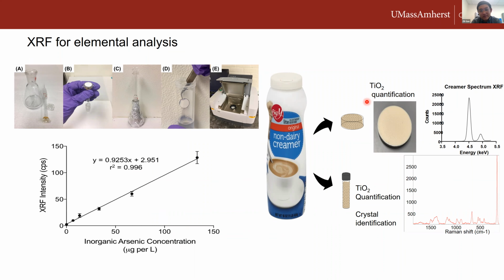It is very similar to Raman. It will be minimally invasive to your samples. Usually, you don't need a very complicated sample preparation procedure. Sometimes you can directly measure your sample in the XRF instrument. The detection limit for XRF can be down to the ppm level. However, in this case, if you're looking on the left-hand side, we successfully detected inorganic arsenic concentration down to ppb levels. So with a better sample preparation procedure or a very good concentration method, we can successfully detect any heavy metal or harmful elements down to ppb level.